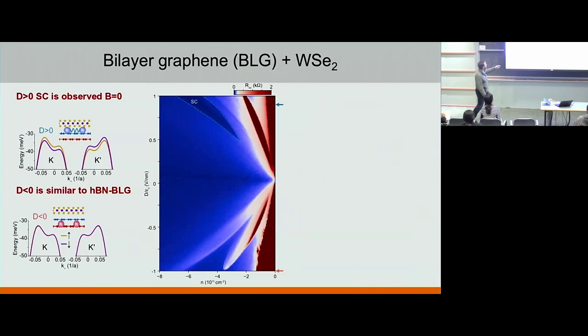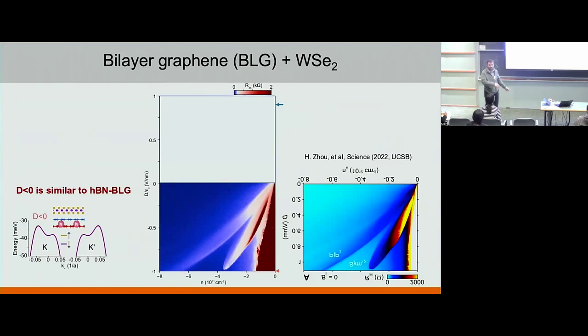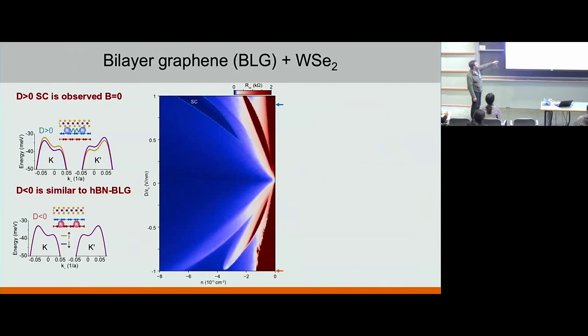On the other hand, if you apply displacement field in the direction that polarizes toward tungsten selenide, in addition to a somewhat modified phase diagram, you have this large pocket of superconductivity, which was the subject of this work. Superconductivity on this side you can only get if you apply an in-plane magnetic field, and it has a Tc, at least measured in this paper, of 30 millikelvin. Today I'm going to show you some data where the superconductivity can approach half a Kelvin.